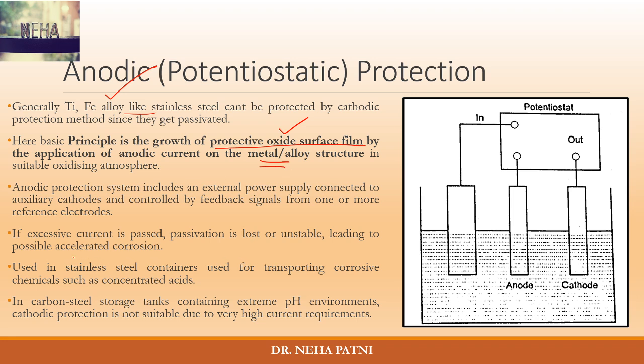That protective oxide film is how the metal gets protected. We have to be careful about the current, because if excessive current is passed, the passivation would be lost, and that will intensify the corrosion. This potentiostatic protection is a very effective method and is used in stainless steel containers and carbon steel storage tanks.